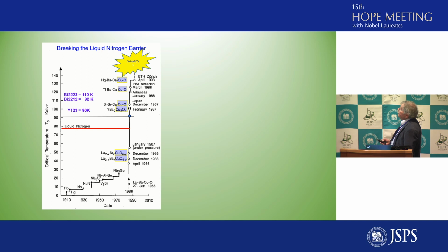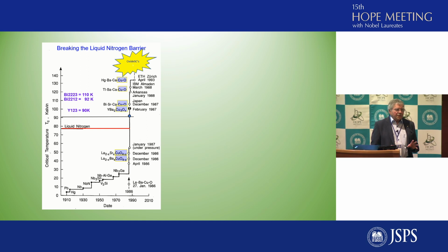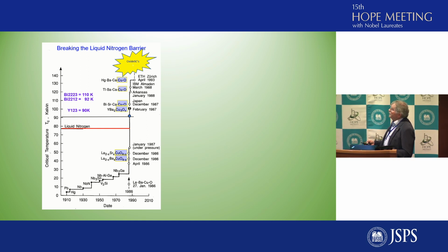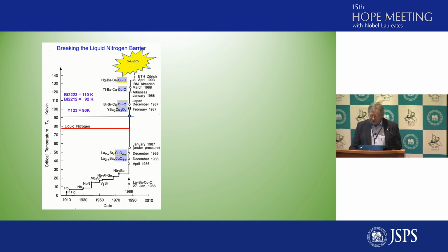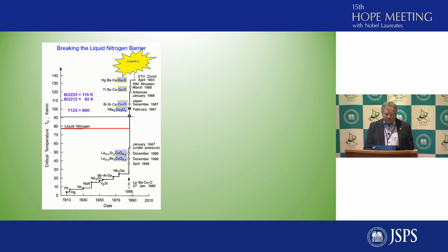And with all the groups which were joining the activities, the temperature was rising very rapidly to more than 135 degrees Kelvin. But the remarkable thing about all of these new compounds is that they are all based on the same building block, the copper oxides, which have been discovered to be essential for the superconductivity. The copper polyhedra are remaining as a main building block, and only the cations on the A side are varied.